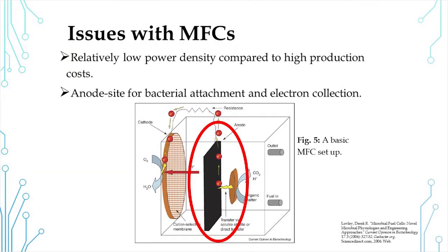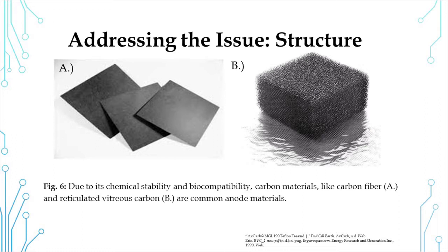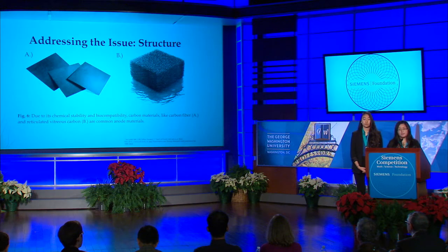However, despite these capabilities, current MFCs are not ready for commercial use because they produce relatively low power densities and use high-cost materials. So the anode requires further development because it is a site for bacterial attachment. One of the most commonly used materials for MFC anodes is carbon because it's chemically stable and biocompatible. Recent studies show that reticulated vitreous carbon, or RVC, a porous structure, has higher power densities because it has a higher surface area, which allows for more bacteria to adhere onto the anode. However, its power density is still low compared to its costs.